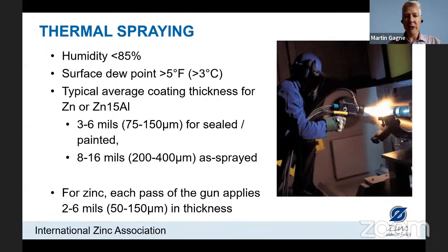With thermal spraying, each pass of the gun generally provides 100 microns of thickness in any case. So with just one pass, we can be ready for painting or sealing. And there is no curing time with thermal spray zinc. It is ready to be painted immediately after application. But if we want to only use the thermal spray zinc for corrosion protection, we should have a slightly thicker coating or twice the coating. So that will mean reapplying another layer of zinc.